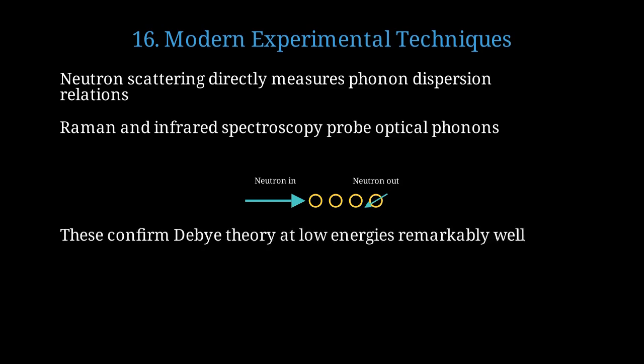Modern experiments probe phonons directly with remarkable precision. Inelastic neutron scattering allows us to directly measure phonon energies and momenta throughout the Brillouin zone. Raman and infrared spectroscopy techniques directly measure optical phonon frequencies in crystals. A neutron scatters from the crystal, exchanging energy and momentum with phonons, revealing the complete phonon spectrum. Remarkably, these modern experiments confirm that Debye's simple theory accurately describes low-energy phonons in most materials.